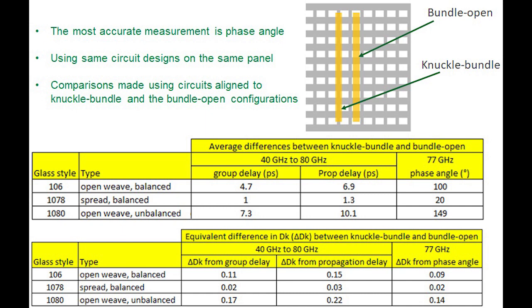The reason we use rolled copper is because we know that copper surface roughness impacts performance, especially at millimeter wave frequencies, and rolled copper is so smooth that whatever variation there could be from one batch of copper to the other will be extremely small and will not impact the influence when we're looking at multiple different circuits and comparing them. So the data that I'm showing here is a table of information, and it's looking at these different circuits that we built on three different laminates.